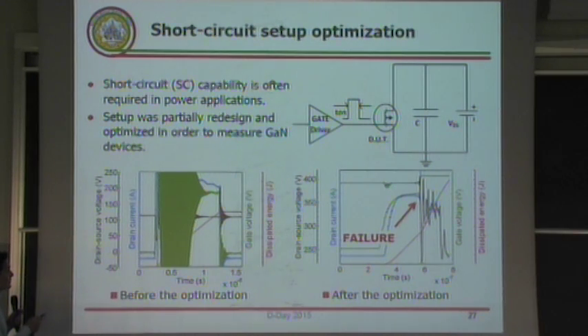However, unfortunately, we started using an old setup which was used for the characterization of silicon devices. And when we put in a gallium nitride device, since these devices are really, really fast, much faster than silicon ones, we observed many oscillations. And so the measurement was not possible. So I took care of the optimization of the system. I partially redesigned the system, and particularly the gate driver.